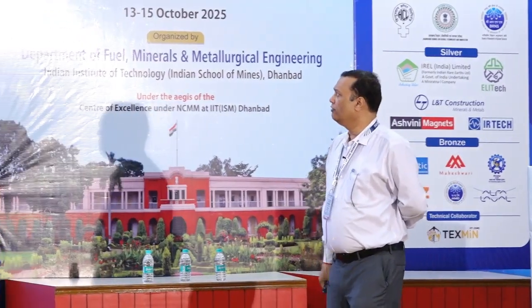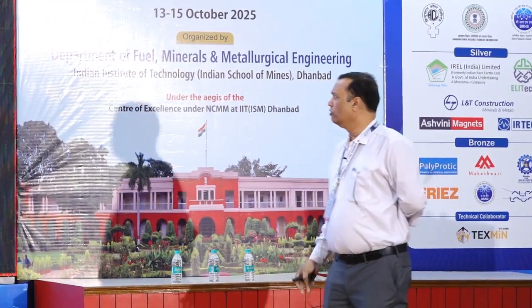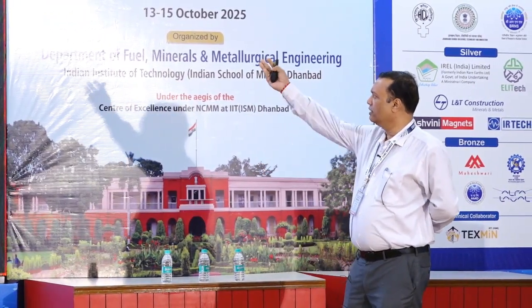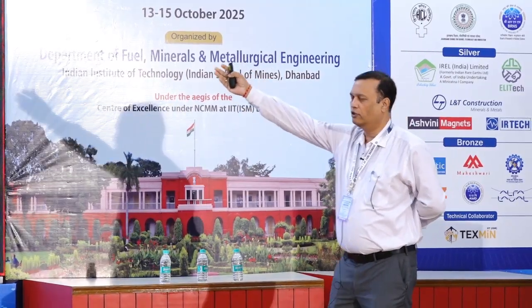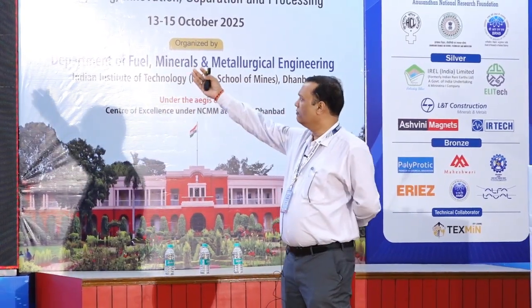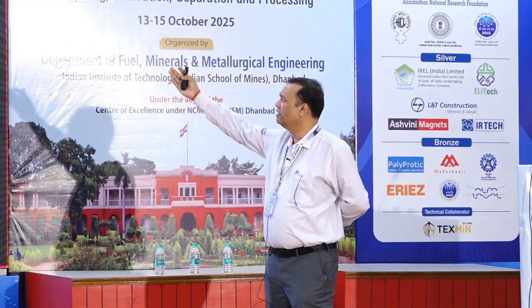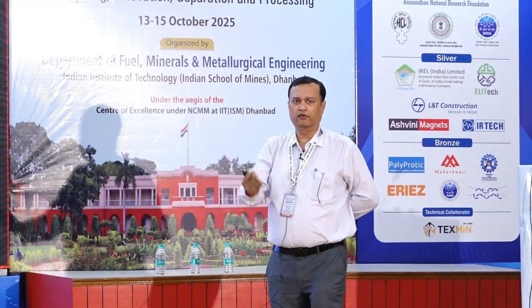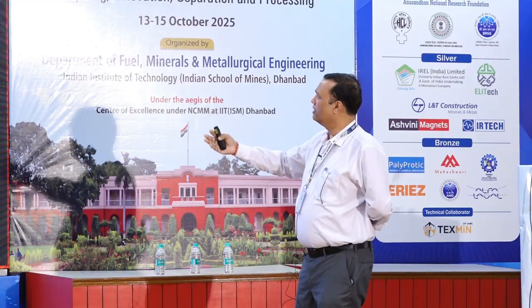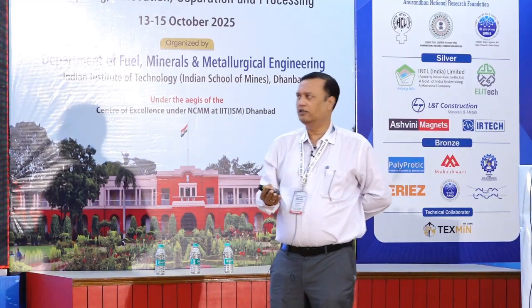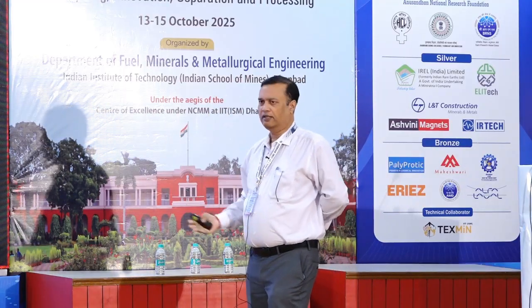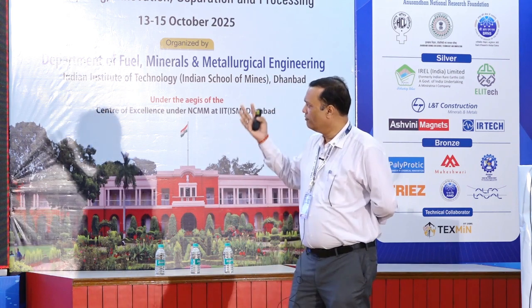So coming to NdFeB magnets. If you look at the microstructure of an NdFeB magnet, it has three major phases. The matrix phase is the Nd2Fe14B phase, whereas at the grain boundary we have the Nd-rich phase, and then we have some boride phases also. And apart from that, because rare earths are highly reactive in nature, we will have oxides, and sometimes an iron phase also. So many phases are there.